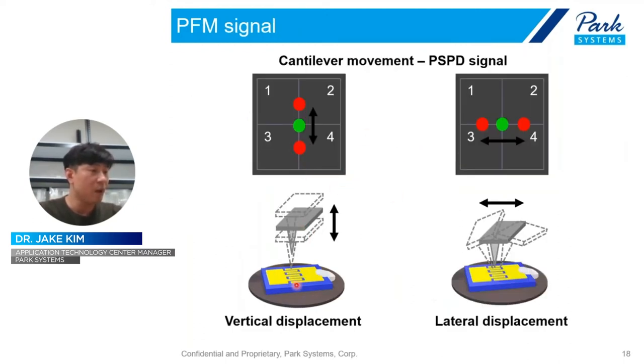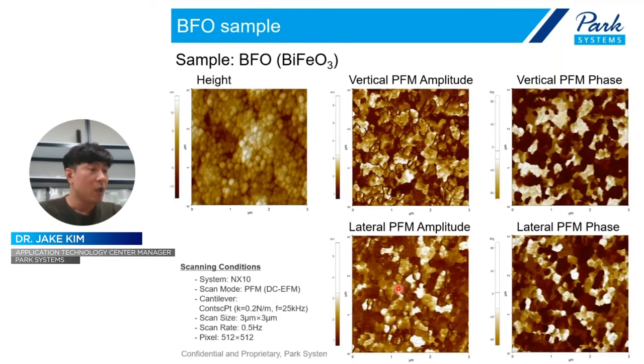Like this, we can investigate the vertical and lateral displacement of the piezo sample and make an image of piezo signal contrast. There is one example. It is a quite famous piezo or ferroelectric material, bismuth ferrite, or we also can call it BFO. And like this, we can see totally different aspects between height, vertical, and lateral PFM signal. So like this, using PFM, we can monitor them on the nanoscale.